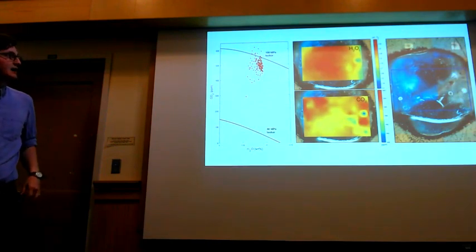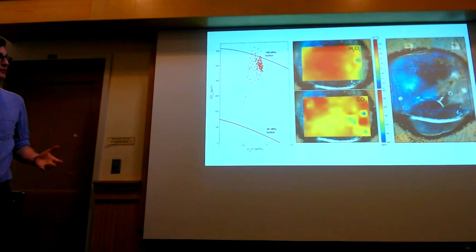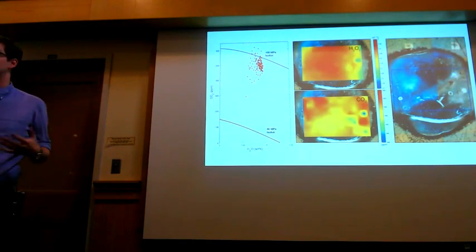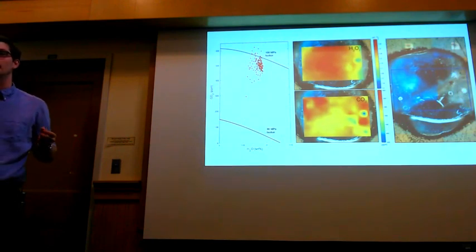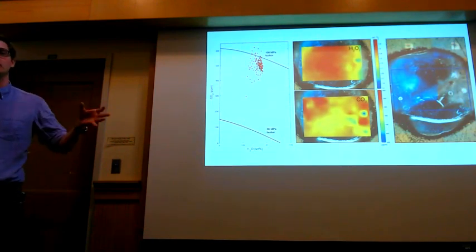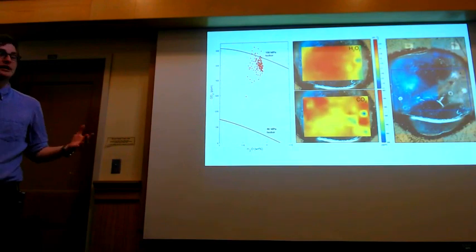And we ended up with gradients of water and carbon dioxide. And so these are all measured by FTIR, or Fourier transform infrared analysis, which has the great benefit of letting us make these area maps here. So we can really look at how these chemical gradients change spatially.